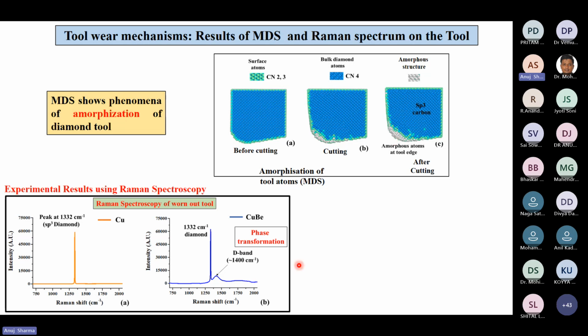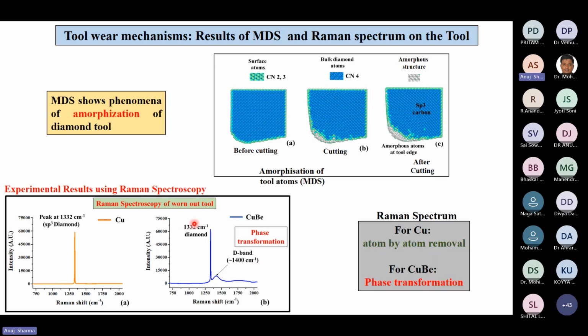It was also seen with the help of experiments. When I carried out Raman spectroscopy on the tool used for copper as well as copper beryllium, it was seen that for copper there was only a single peak. That showed that only sp3 diamond was there on the tool. But in the case of copper beryllium, the tool showed one single larger peak that corresponds to diamond, but there was another peak that corresponds to the D band, or amorphization of the diamond. So some amorphous layer was formed, which was shown with the help of experiments as well. So we can state that for copper there is atom by atom removal of tool atoms, and for copper beryllium the tool wear takes place by phase transformation.